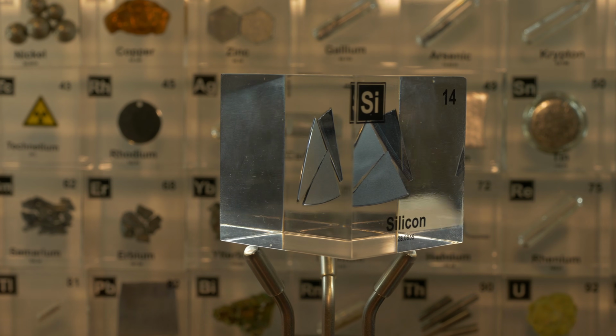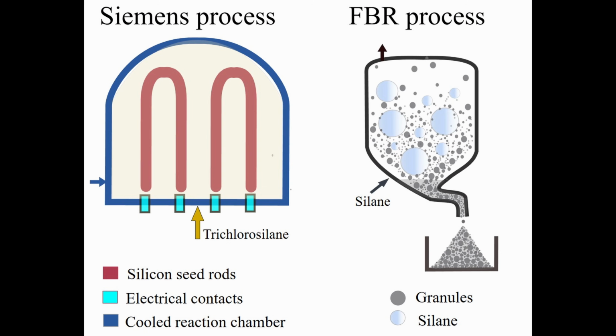One common purification method is the Siemens process, developed in the 1950s. In this process, the impure silicon is first converted into a volatile compound, then filtered, then decomposed back into pure silicon. Typically, the crude silicon is reacted with chlorine or hydrogen chloride gas to form chlorosilanes. These are compounds like silicon tetrachloride or trichlorosilane. For instance, silicon tetrachloride can be made by chlorinating silicon, and tetrachlorosilane often comes as a byproduct from making silicones. These silicon compounds are liquids or gases that can be distilled to remove impurities. Impurities either don't form volatile chlorides or form heavier ones that separate out.